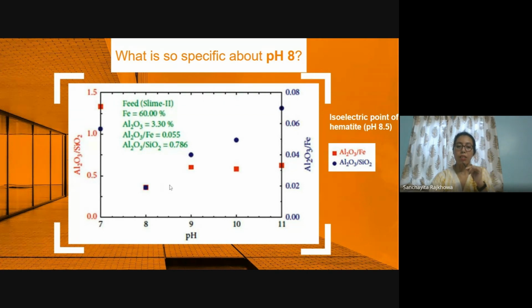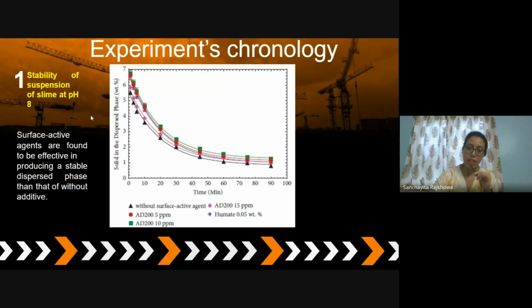Now, these are several experiments that we have done with the suspension. First, we have done the stability of suspension of the slime at that particular pH, and we have studied the amount of surfactant agent, and we have found that these amounts are very effective in producing a stable dispersed phase rather than without the surfactant.